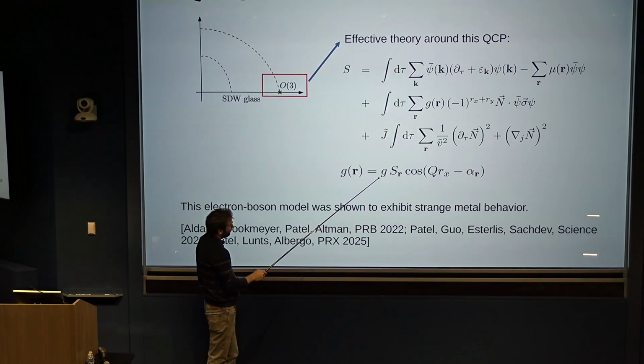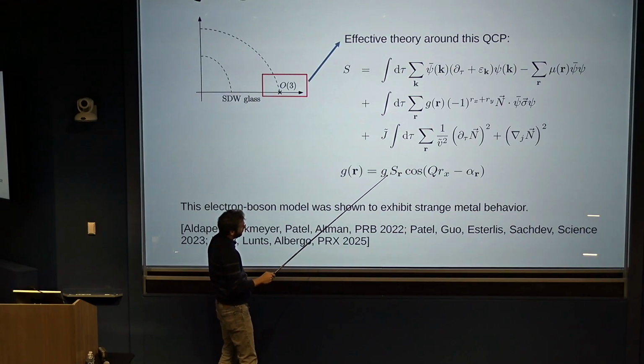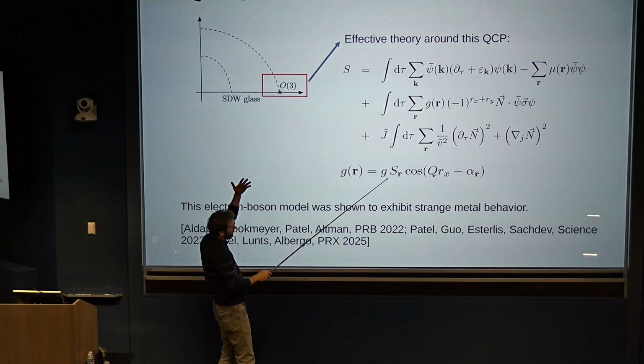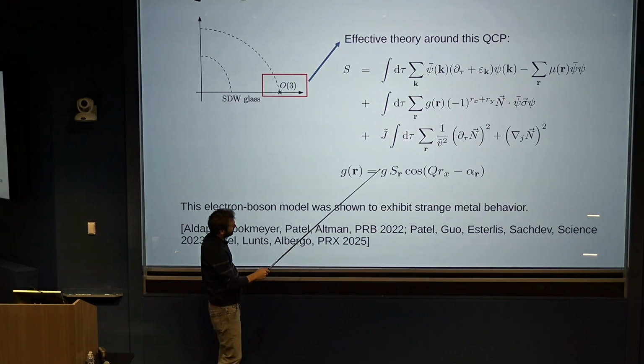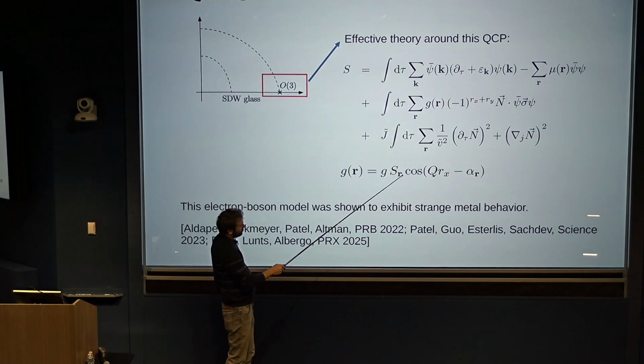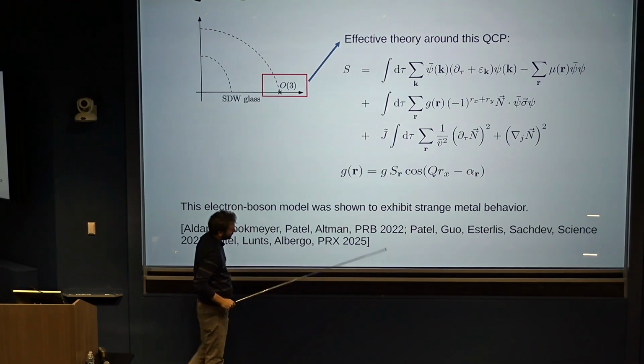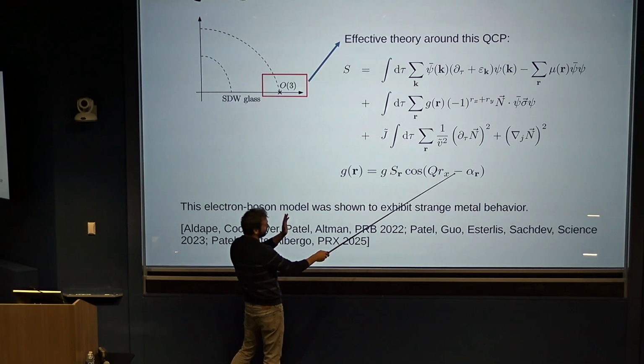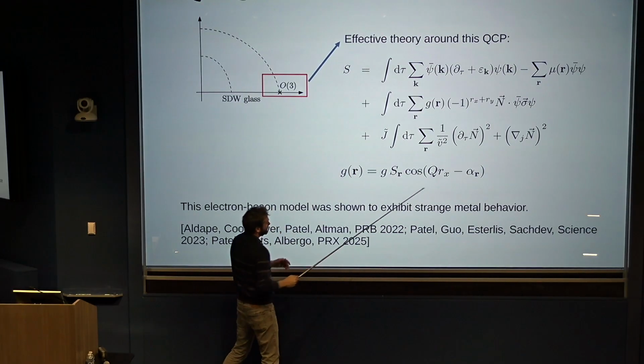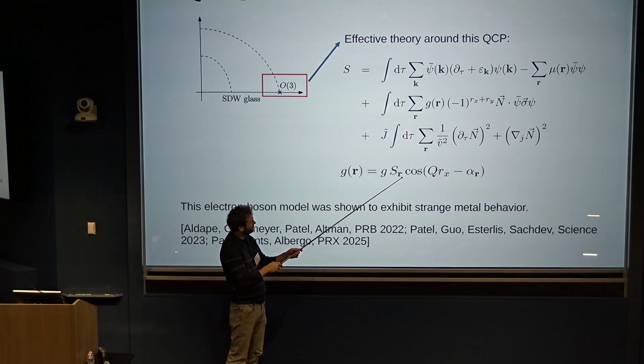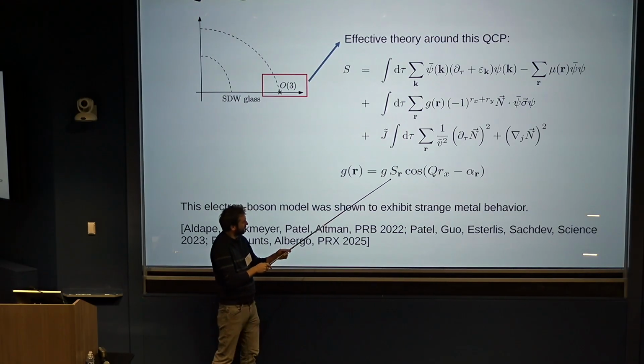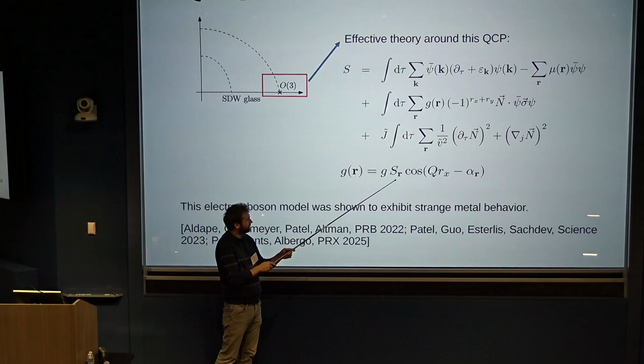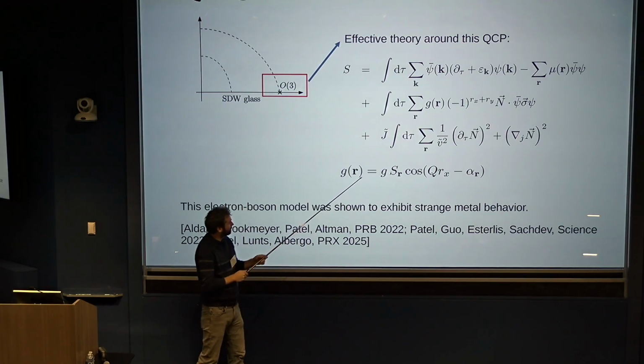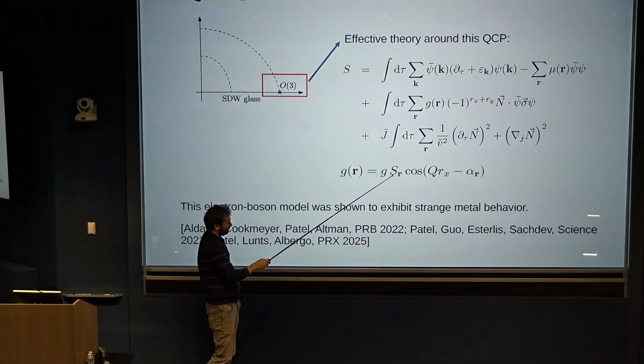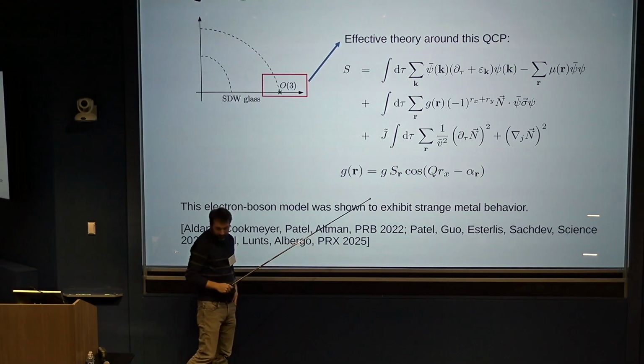Before, we started out with a Landau-Ginzburg-Hertz-Millis theory with a constant G, from the UV theory. But now the effective G_r is this constant coupling times S_r. This is basically the Ising spin degree of freedom. And then there's some cosine, which doesn't matter; it comes from the disorder as well. But the important thing is this Ising degree of freedom, which is in a random Ising spin glass configuration. So you now get a coupling constant which varies randomly from point to point.